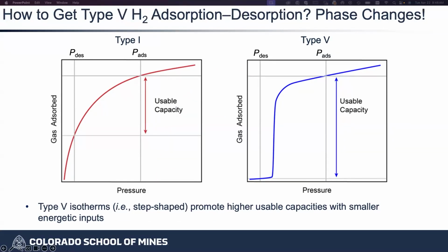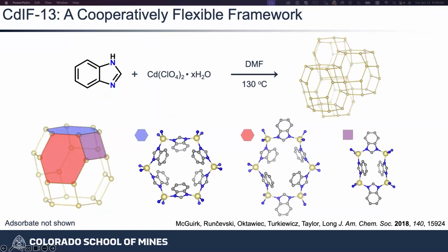And so the reason why I tell you about this is because we've been doing these with metal organic frameworks. Specifically, most of the work that we've been doing is based on this system called CdIF-13. So CdIF-13 is actually a material I discovered when I was a postdoc, and it's just been a wealth of a platform in order to study and build out our understanding and its utility. And so very simply, we have this benzimidazolate-based linker with a cadmium-2 salt, and we make this sodalite topology. And because we have these relatively weak cadmium-nitrogen bonds that are kind of the coordination skeleton in the system, we were able to get really beautiful single crystals.